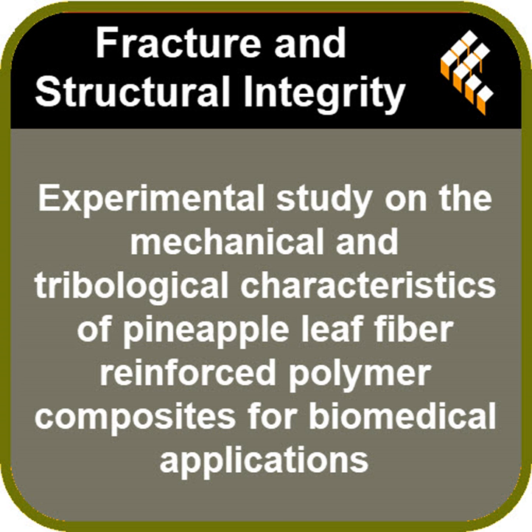Exactly. They looked at the fractures under a scanning electron microscope. And when a microcrack forms, the fibers literally stretch across the gap. They stop the crack from spreading. They stop it in its tracks. The material with 25% fiber could absorb almost double the impact energy. It's tough, not just strong.